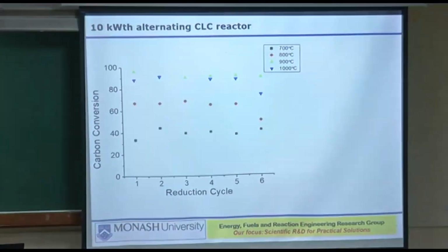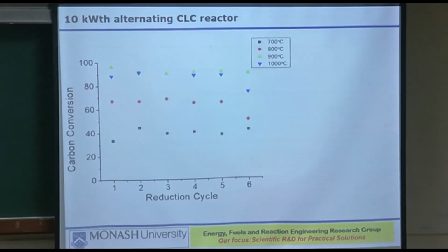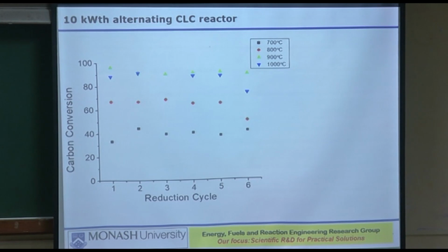So what then he did, this another student actually did. He did run it there at different temperatures deliberately, at 700 bed temperature, 800, 900, and 1000, trying to see how much carbon conversion, no carbon stripper business, no steam injection, nothing, just the normal fuel reactor conditions, how much carbon conversion you can achieve as a function of operating temperature inside the fuel reactor. Whatever cannot be achieved will be converted in the carbon stripper. So it's valuable information. Now in this experiment, no steam.